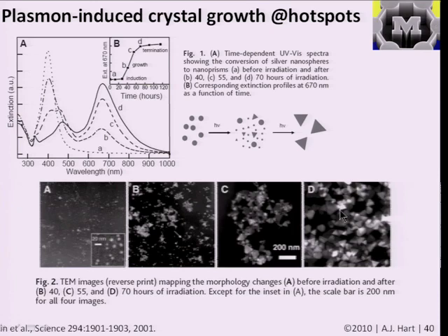And they found that when they had effectively exhausted all the silver from the solution, all the source material, then the size increase of the structure stopped. And so it was a pretty slow process. It took a few days. Like, as you can see, it kind of happened over a weekend, about 50 hours or so.